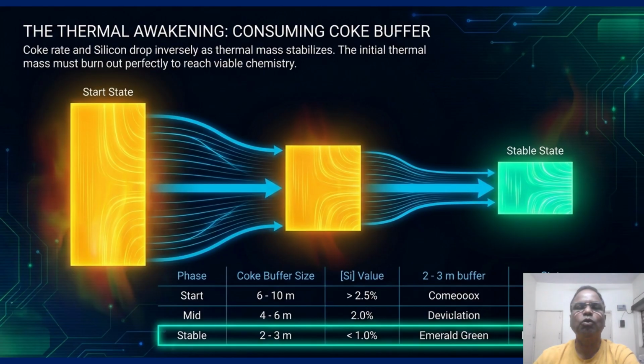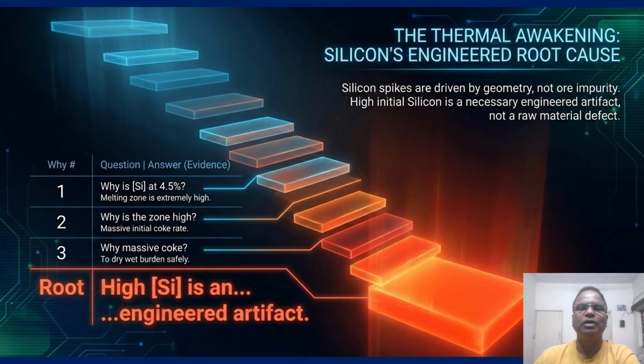The initial coke buffer protects the hearth heat, but it must burn down at the right pace. Too fast causes chilling and too slow keeps silicon high. So we need to optimize the minimal burning intensity rate, and that gives us a good solution.